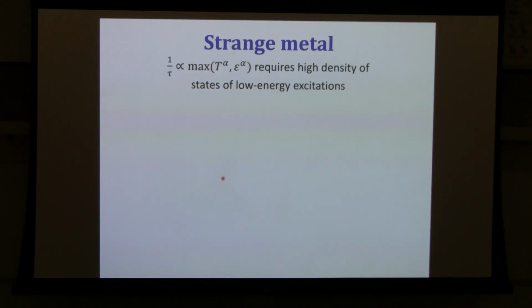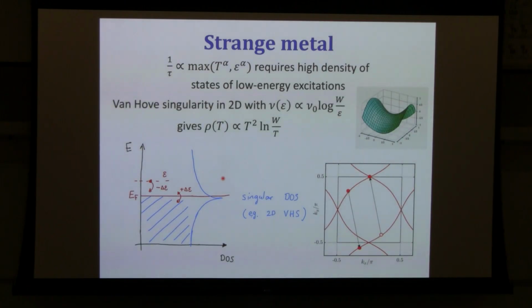Okay, so here's an example of a relatively mundane way to get a deviation from Fermi liquid theory down to low temperatures. Suppose that we tune our system somehow into a saddle point in the electronic dispersion. Okay, so what's a saddle point? So this is the Brillouin zone. And there are some special values of some parameters, say the electron density. I'll show how to do it in experiment in the next slide, where this is an example of a 2D metal. And what happens here is that the Fermi surface changes its topology from electron-like to hole-like. So basically, the Fermi surface reconnects with itself here and undergoes this topological transition.